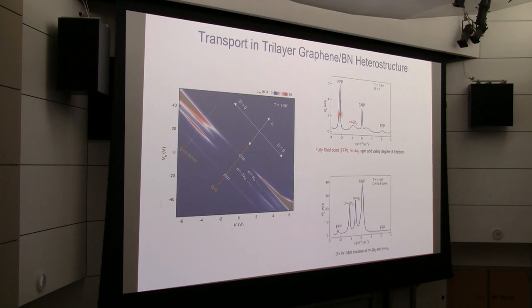Now if we increase the vertical electric field, we effectively squeeze the band and increase the correlation. And we can see transport change very dramatically. You start to see well-defined resistance peaks at 1 hole per lattice site and 2 holes per lattice site. In particular, 1 hole per lattice site is a canonical configuration of a Mott insulator. So you can actually have a continuous metal-insulator transition when you go along the direction of finite electric field. And once the bandwidth is narrow enough, you can have reliable Mott insulators.